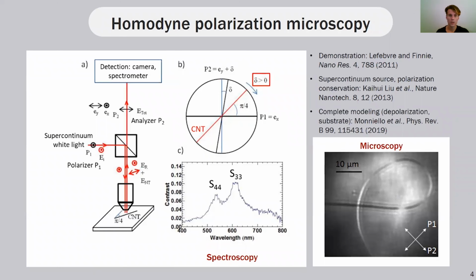In our turn, we use a method which was developed by the group of Lefebvre and Finnie in Ottawa and Kaihui Liu at the University of Berkeley. It is based on strong optical anisotropy of carbon nanotubes, which allows separating their signal from the background. We use a supercontinuum or white laser to excite all nanotubes in the visible spectrum and to suppress the light scattered and reflected by the substrate. We use two cross polarizers. The weak signal of the nanotube is further amplified by homodyne, or by interferential coupling with reflected light, hence the name of the technique: homodyne polarization microscopy.